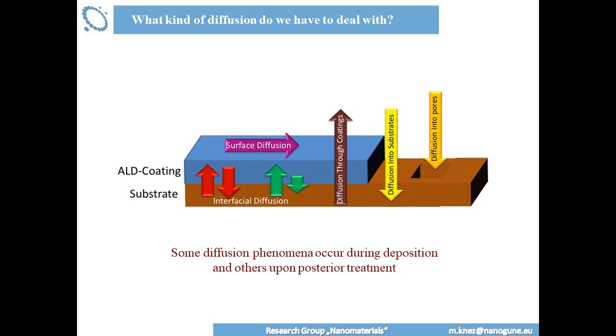I put together those diffusion phenomena which I found being of interest and of importance for most of these, let's say, special processes where you want to prepare some functional samples. And those relate mainly to surface diffusion. This is, I think, a very common thing. Go a little bit into that. This is happening during the process. Then you have the possibility to diffuse material into a substrate. This is also happening during the process, in most of the cases. Diffusion into pores is a very critical issue if you don't have flat substrates. Again, this is an issue which happens during the deposition.